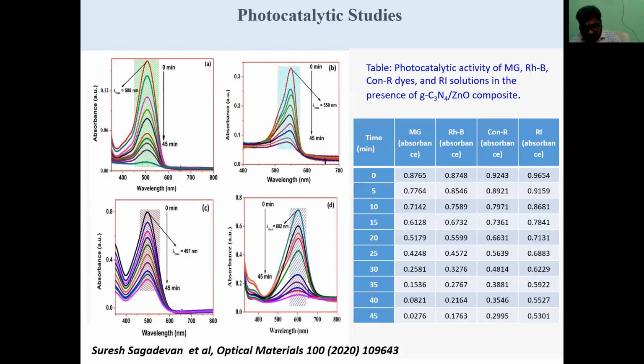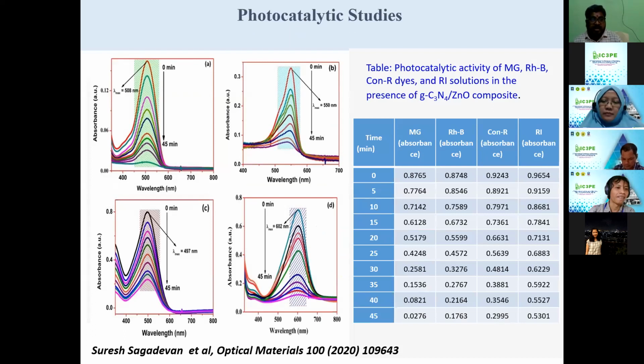Now you can see the very interesting photocatalytic studies of graphene carbon nitride with zinc oxide, where UV light is illuminated for a time period of 0 to 45 minutes. You can see here A, B, C and D are used for different dyes. A is malachite green, B is rhodamine B, C is Congo red, and D is a red ink solution. You can see from the figure the different solutions, MG, RhB, Congo red dyes and RI solutions, over different time periods, as in the table: 0, 5, 10, 15, 20, 25, 30, and 40.